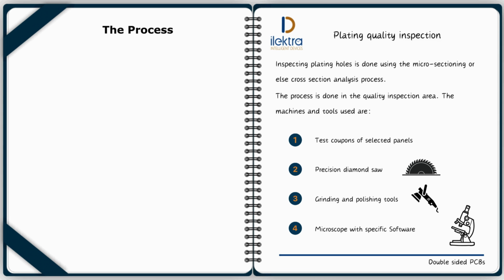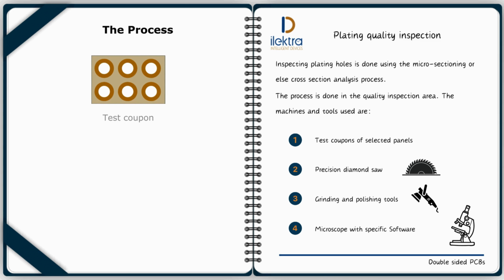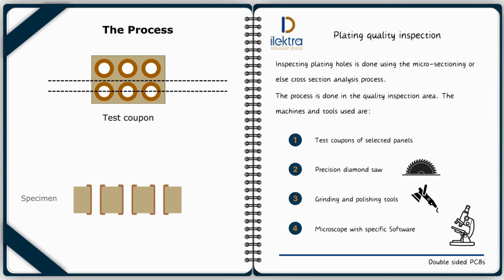Micro-sectioning is a sample destructive process. It starts with cutting a thin cross-section piece out of the coupon using a diamond saw to create a test specimen. The specimen is embedded in resin for easy handling. Then, the surface is grinded and polished to create a very smooth light reflective surface that can be placed under the microscope. The image of the cross-section, showing the plated walls, is inspected and copper-plated thickness is measured using the specific software. If everything is okay, the panels are ready for solder mask application.